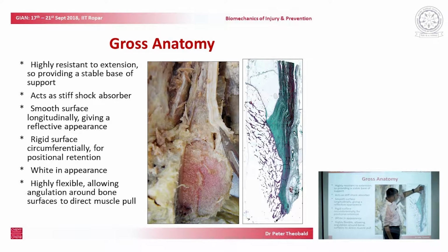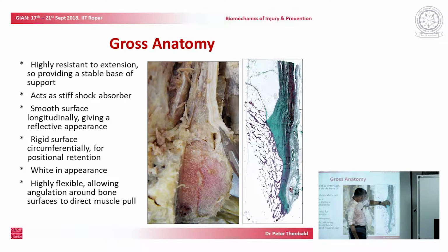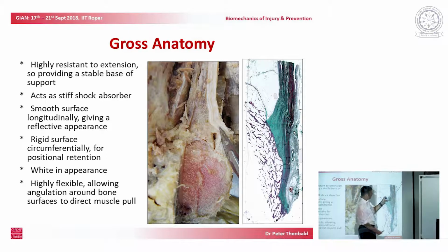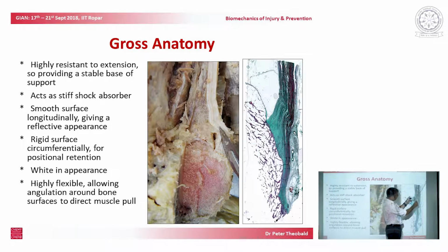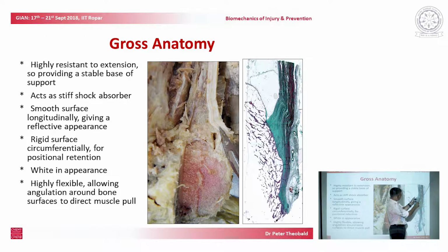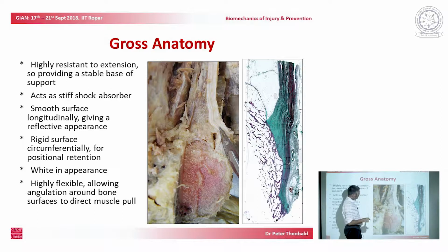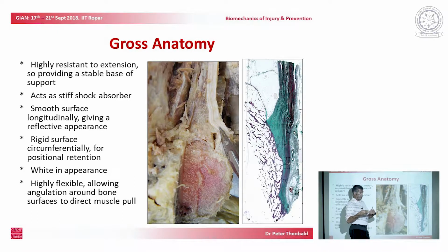And so we have a relatively unstiff tendon, a relatively stiff tendon, and then a very stiff bone, which is very similar to our relatively unstiff cable, our relatively stiff grommet, and then our very stiff box. And that interface, and also the fact that if we were to zoom in closer, we can see red parts projecting into the green parts of the tendon, means that we're not talking about a simple interface that one has been effectively glued onto the other. They're actually interlocking. And so the contact area between the two different tissues has been expanded, and so the strength is greater still.